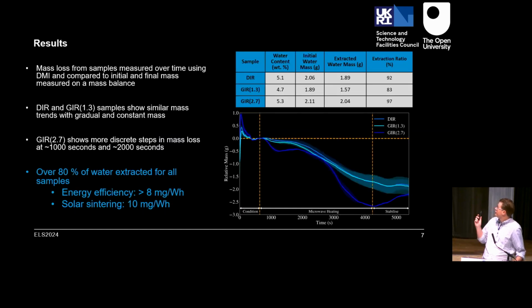First thing to note, if you look at the table on the top right, these mass measurements are using the old system where I just measured the mass before and after. The first thing to mention, if you look at the extraction ratio, is that the extraction is quite high for all of them, and there's actually not a great deal of difference between them. This is a good thing for microwave heating in terms of its water extraction potential, in that it doesn't really matter what type of water ice we end up finding. It should still be okay at extracting them fairly consistently.